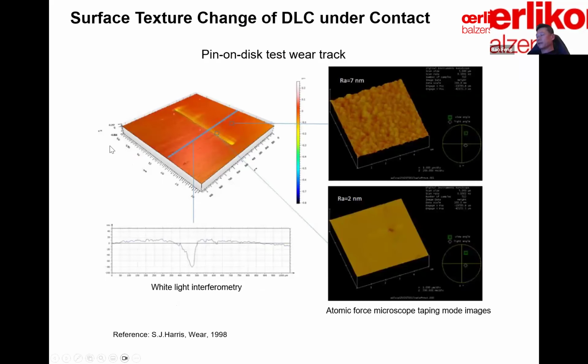There's another piece of evidence to confirm that behavior. If you put this contact surface, the coated surface, under an atomic force microscope, you can see at a nanometer scale what the surface looks like. It started as a surface with bumpy texture, like sandpaper. After breaking in itself and the counter surface, that surface will become ideally mirror-like, even at a nanometer scale. If we look at it, there's a 2 nanometer surface roughness. And at that time, the coated surface will lose its capabilities because it's so slippery.